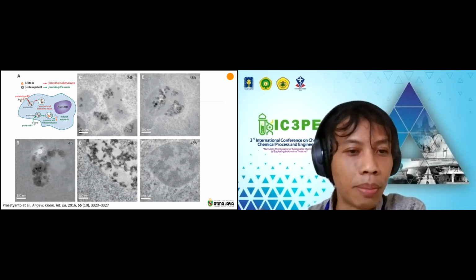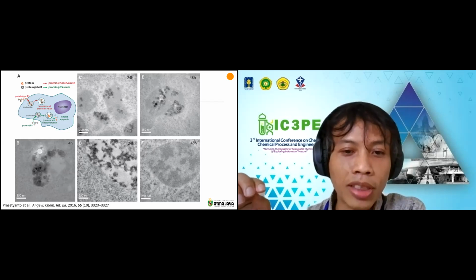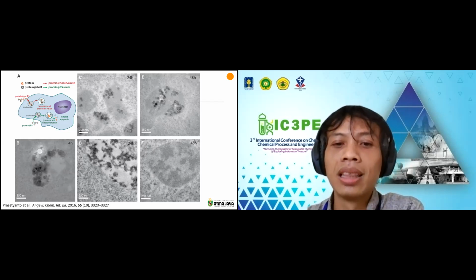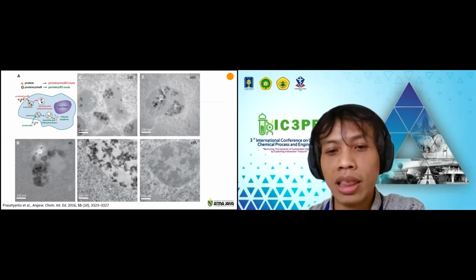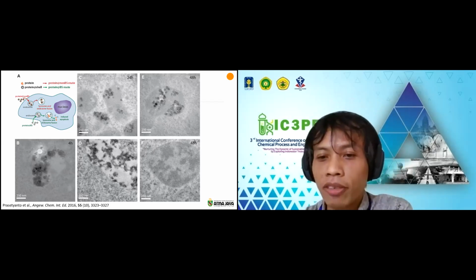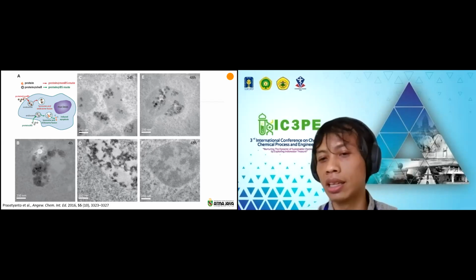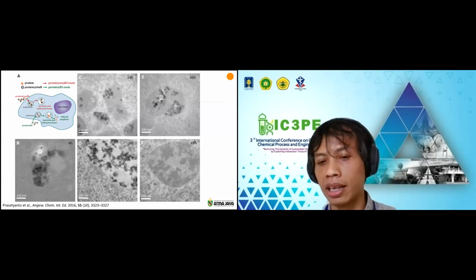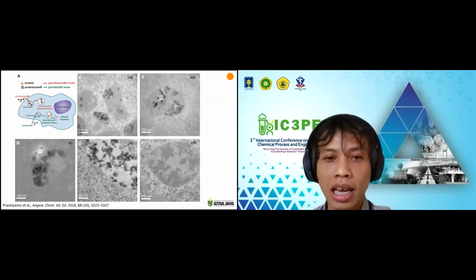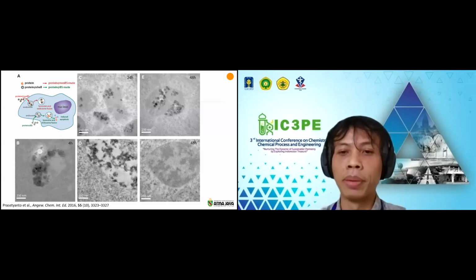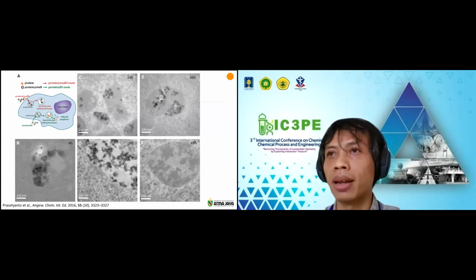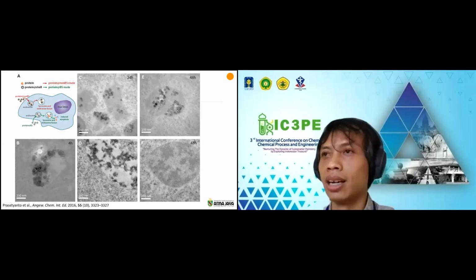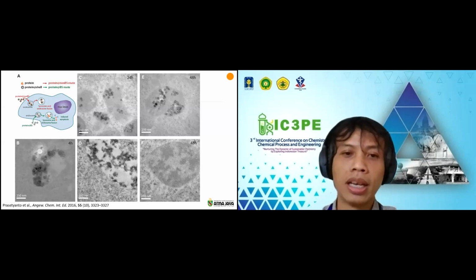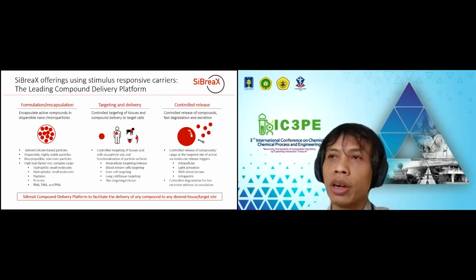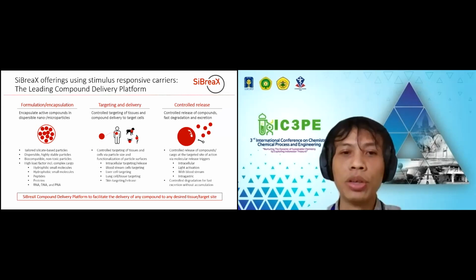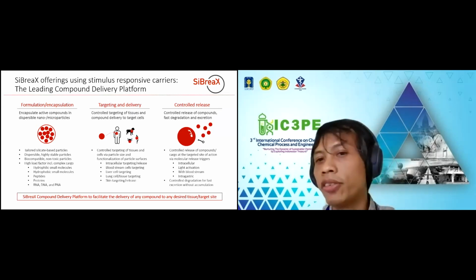However, in the bottom one, after 24 hours, we already can see the deformation of the cell and the deformation of the nanoparticle. And then after 48 hours, it's clear that we could not find any silica nanoparticle inside of the cell. So it means that our breakable nanoparticle can really break apart inside of the cell and clear from the living cell. So now this finding we use as a targeting and delivery, and also for control release.